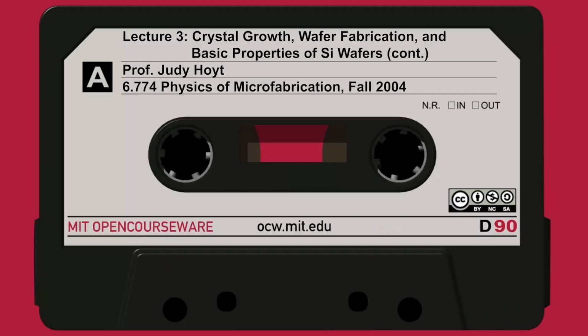There are two other things about the crystal that are very important that I wanted to discuss, covered in chapter 3, and that is oxygen and carbon. We said on Tuesday that the Czochralski growth process inherently introduces oxygen from the quartz crucible and a certain amount of carbon. We can't get around that. These are typical numbers: oxygen about 10 to the 18th, carbon concentration about 10 to the 16th. They both have some important effects. For example, for oxygen, these are 3 effects that are listed.